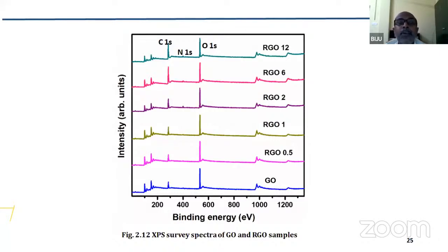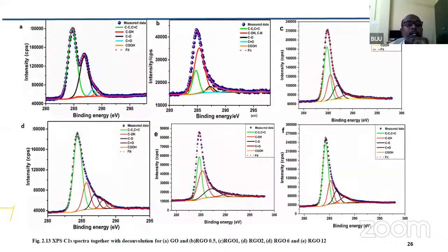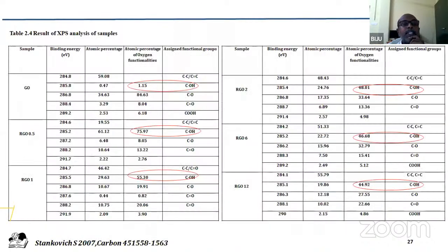Now we did the XPS analysis to see what oxygen functionalities are present, as well as to quantify them. So these are the carbon XPS of all the samples, and the results are summarized. See, the GO as well as all other samples contain C-OH, C-O, C double bond O, and COOH, other than the carbon-carbon single and double bonds. Now let us concentrate only on one point, that is the atomic percentage of OH. GO contains OH of only 1.15%, whereas as the reduction proceeded, the OH content suddenly increased to 75.97%. So in RGO 0.5, the OH group was 75.97%, and then it gradually decreased.